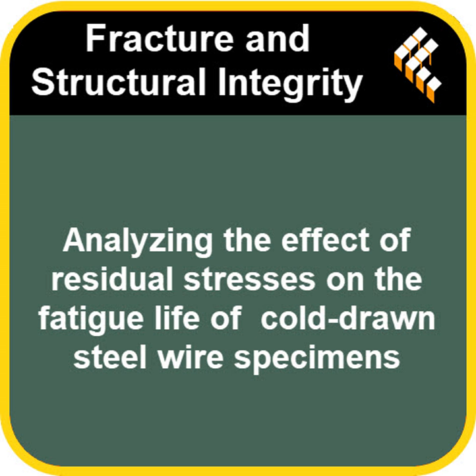Okay, that's genuinely surprising. So their model, designed to predict this, was way off. Why? That was the big question. And it forced them to revisit their initial assumptions. The key assumption they'd made was that the wires, as they got them from the manufacturer, did not have appreciable residual stress. They assumed they were starting close to zero stress internally. And that assumption was wrong. Completely wrong, it turns out. The aha moment. Exactly. They realized that the residual stresses they put in during phase 1 weren't enough to wipe out beneficial compressive residual stresses that were already there. Already there from?